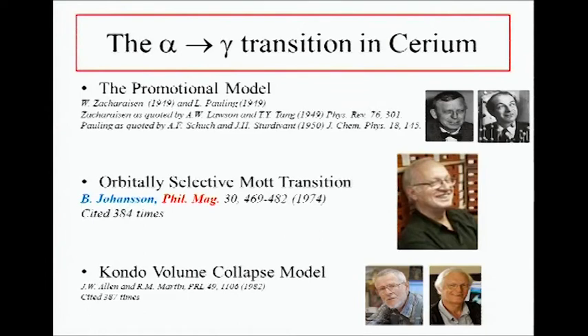From the theory point of view, the first suggestion was the promotional model by Zachariasen and Pauling independently in '49, where they basically suggested what happened in this material was that the 4F level was degenerate with the conduction band, so it was very easy to squeeze electrons out of the conduction band into the F band, at which point there's a decrease in bonding and a volume collapse, and the occurrence of more magnetic F character. So this was the original picture.